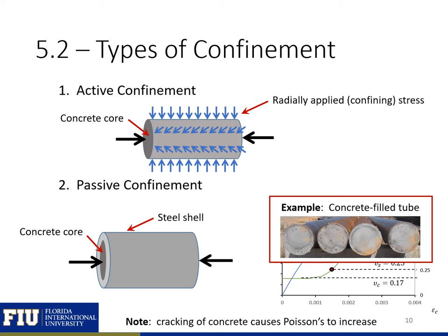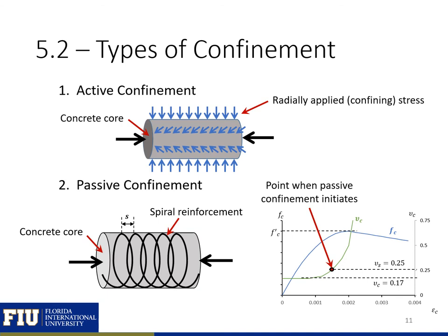One example of near-perfect passive confinement is concrete-filled tubes. These elements have a steel tube on the outside and concrete and reinforcement on the inside, and they're currently being used in some applications for bridge columns and piers. A steel tube may provide the best passive confinement for a reinforced concrete column, but we don't always have a steel tube, so we'll look at how to account for the confinement effects provided by spiral reinforcement and by regular rectangular stirrups or ties.